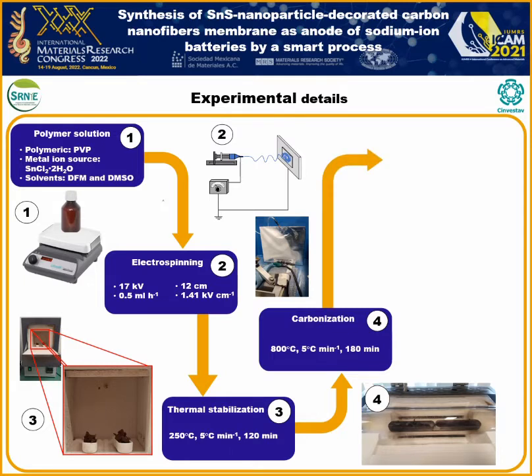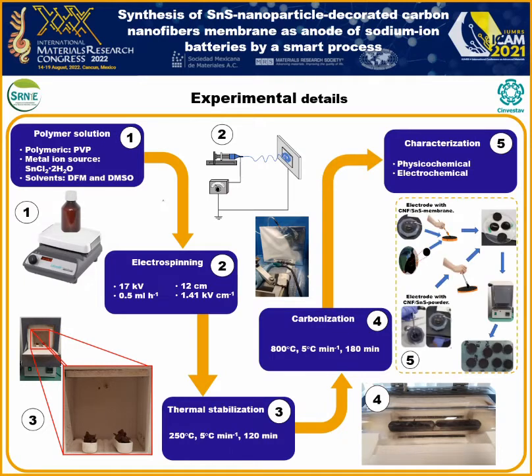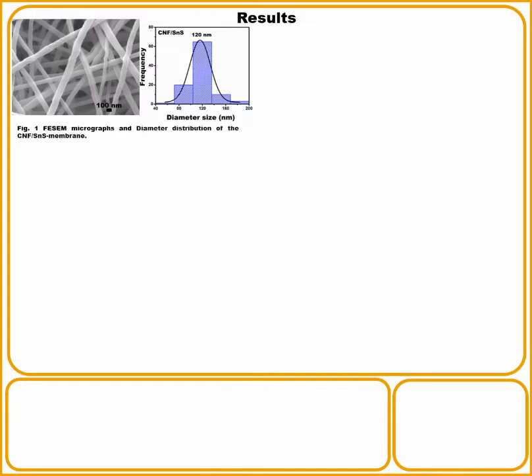Finally, the carbon nanofiber membrane with tin sulfide was characterized by using physicochemical analysis and electrochemical measures. In the results, Figure 1 shows the SEM micrograph of the carbon nanofiber membrane with tin sulfide, which has a morphology like long strands with a diameter distribution of about 120 nanometers.